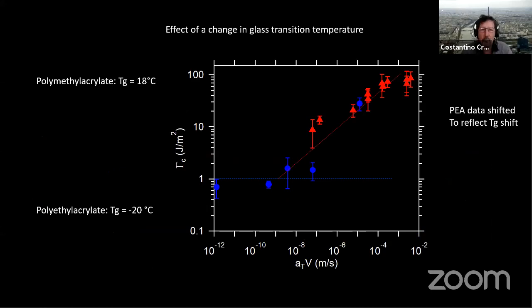One thing we did, we thought, okay, what if we go to a different elastomer? So if we use an elastomer with a lower Tg, in this case minus 20 degrees, can we do the same measurement? And here we can see that if we shift the data to account for the different Tg, so we shift the data by 40 degrees, now we do the experiments at higher temperature relative to Tg, and indeed we break much less bonds. So in a way, these two materials can almost go on the same line. They have different entanglements, so they shouldn't necessarily be on top of each other, but we see that the general trend is the same.